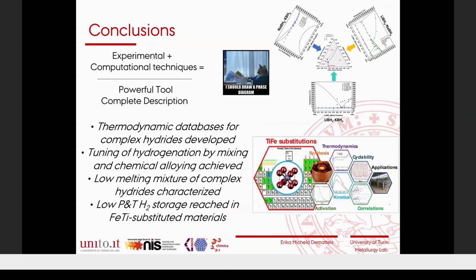So to conclude, we demonstrate that experimental and computational techniques are really powerful tools for a complete description of the thermodynamics of both complex hydride, but also can be exploited to determine the description of intermetallic compounds. We developed thermodynamic databases of complex hydride. We tune also by mixing and chemical alloying the hydrogen release properties and characteristics of these compounds. And we demonstrate that low melting mixtures of complex hydride can be reached at really low temperature. On the other hand, for intermetallic compound, we reach in iron titanium substituted material a low pressure and temperature hydrogen storage that can be performed up to 25 bar and at room temperature. And that's really an advantage for a large scale application.